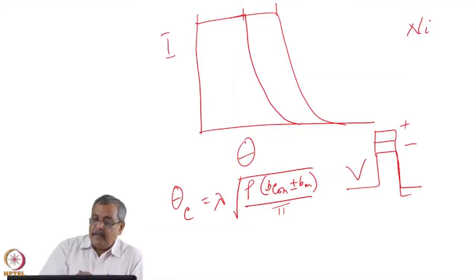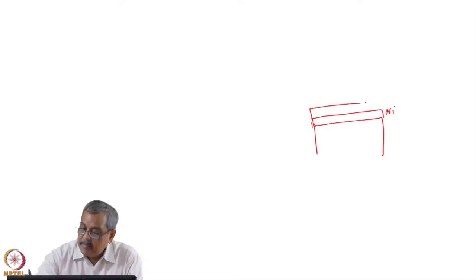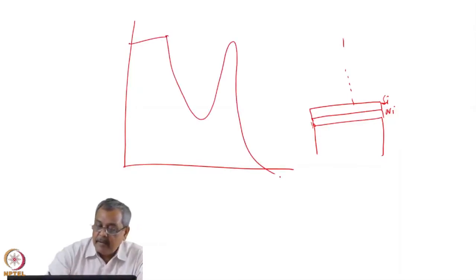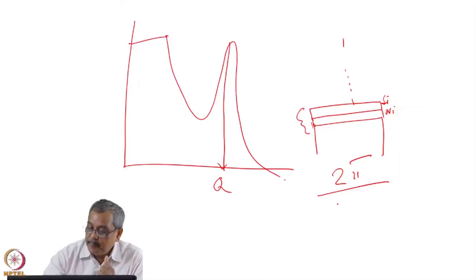Then there is an idea that if I have a bilayer of magnetic and non-magnetic materials, let's say a periodic bilayer of nickel and silicon—nickel is magnetic, silicon is non-magnetic—in that case, apart from the critical angle for nickel, I will also have a Bragg peak depending on the periodicity at a Q value which is commensurate with the D spacing, because 2π by (D_nickel plus D_silicon) will tell us where this Bragg peak will be. This is a periodic bilayer with one periodicity.